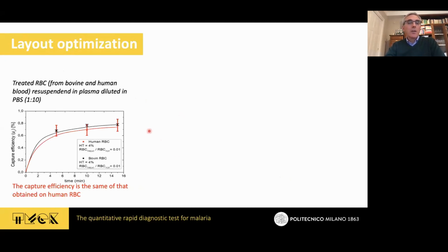Just to make a long story short, the first thing was the validation of the bovine model. In order to do that, here you see two experiments in black and red corresponding to the bovine model and the human model. In this case, we took red blood cells from a bovine blood sample and from a human blood sample. We treated them and created a model of infected blood, and we measured the capture efficiency over time. You see the two curves are superposed within the limits of the error bar, which means that the bovine model was really a good model to use, in order to simplify all the procedures connected to the treatment of human samples, for which you need a sort of ethical committee approval. So it's not so easy to work with a human blood sample.